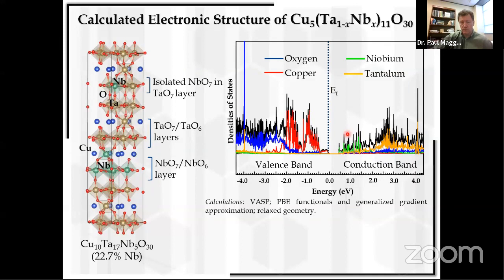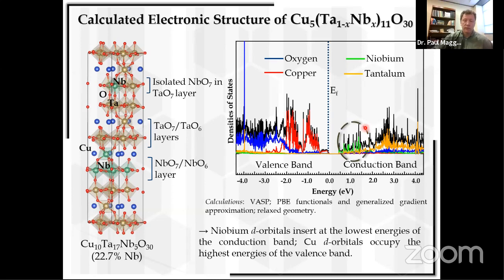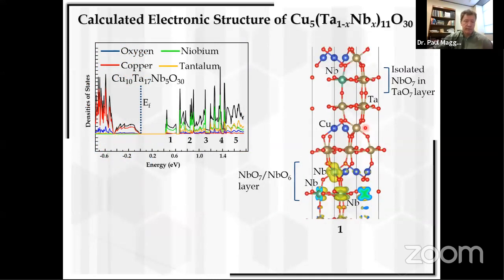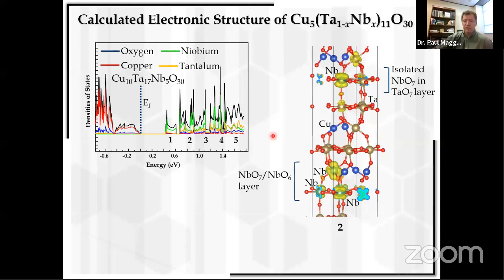Okay, and so let's zoom in on this little part of the densities of states, and see what the contributions are from. Okay. So I've labeled the different regions of the conduction band here, 1 through 5. 1 at the lowest energy of the conduction band, 5 at the highest energy of the conduction band. And so I plot out the electron density contributions arising from this part of the conduction band. And that's the extended niobate network here, right? And so you can see the electron density in yellow. That is what's contributing to the lowest part of that conduction band. Now let's go to 2. We go to 2 and we start seeing contributions from the isolated niobium part of that network.